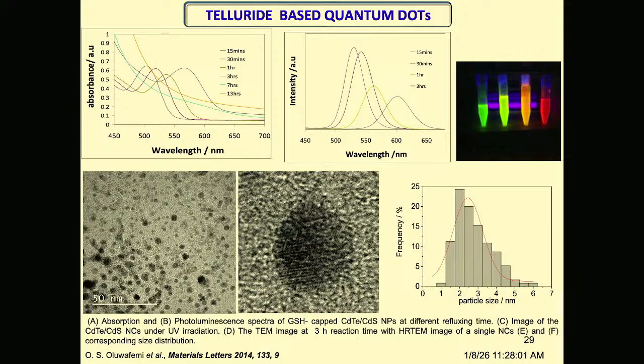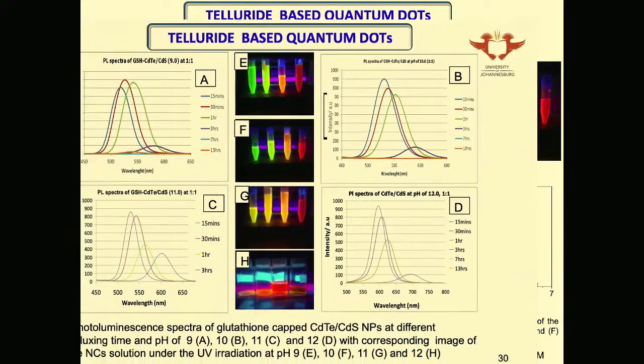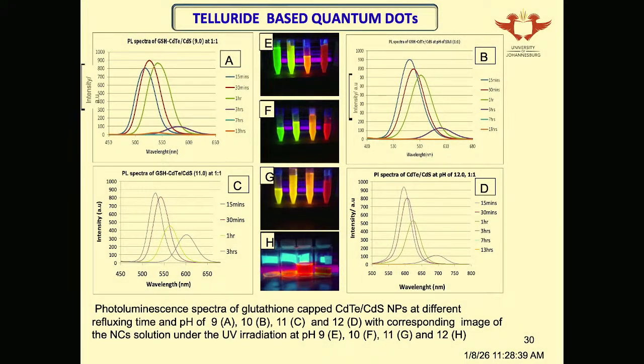So now, we're telling ourselves, what test can we do? 3 hours is too much. Can we reduce the time? And then we look at band engineering. In this case, we decided to look at the effect of pH. And by the time we did that, we discovered that at pH 12, we can produce this material within 1 hour. We can produce the material that can fluoresce in the red.